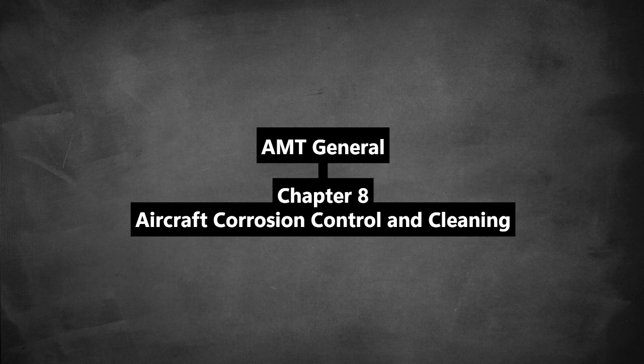Electrocleaning uses an alkaline solution and current. And for aluminum or magnesium, similar prep. Similar methods, yeah. But you have to be careful with blast cleaning on thin aluminum, especially alclad, and never use steel grit on aluminum or stainless steels. Polishing and buffing are also important steps sometimes, especially before plating.